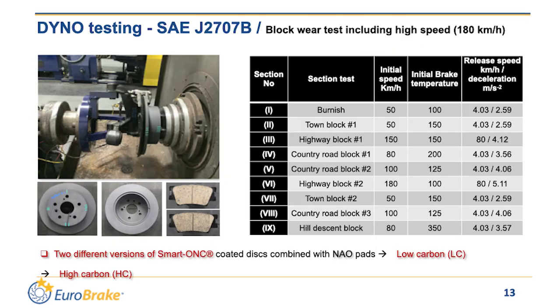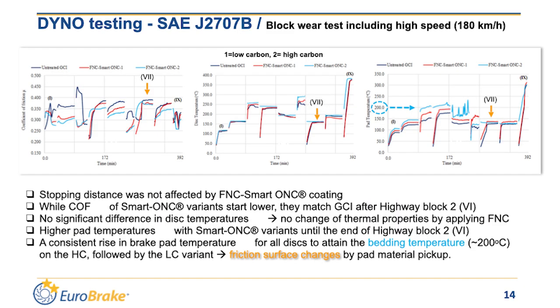For the evaluation of the tribology properties, we did dyno testing according to SAE J2707B on an untreated disk and two different variants of Smart ONC with high and low carbon in the compound layer. Using NAO pads, these tests include 9 steps and different highway blocks with high speeds. The results show that the stopping distance was not affected by applying FNC Smart ONC. Figure 1 shows that the untreated gray cast iron shows the highest coefficient of friction. The Smart ONC starts lower but matched the value of the gray cast iron after highway block 2.